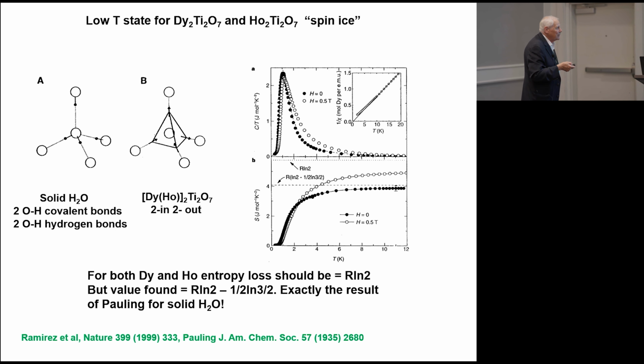And when specific heat is measured, you find that not all the entropy that you expect is there. For both dysprosium and holmium, the ground state is a doublet, so you should be getting an entropy loss equal to R ln 2. In fact, the actual entropy loss is R ln 2 minus 1/2 R ln 3/2, and this is exactly the result that Pauling got many years ago for water ice.